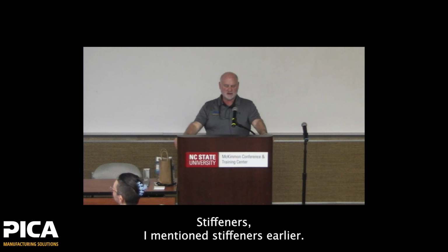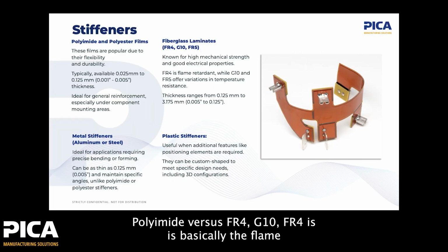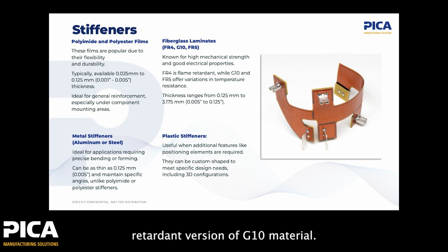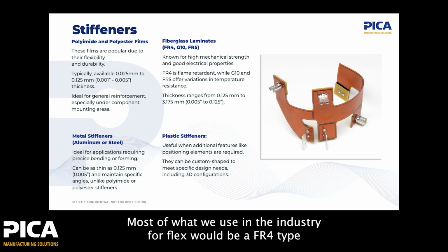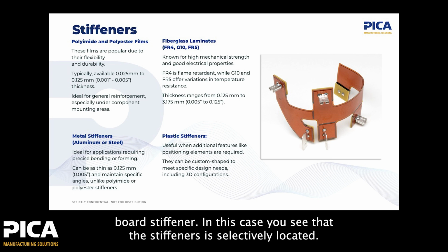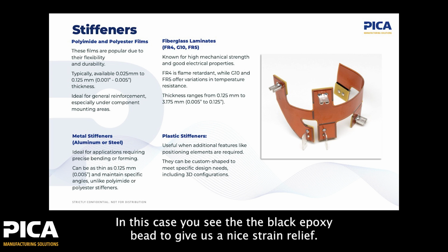Stiffeners. I mentioned stiffeners earlier, Polyimide versus FR4, G10. FR4 is basically the flame retardant version of G10 material. Most of what we use in the industry for flex would be an FR4 type board stiffener. In this case, you see that the stiffener is selectively located. In this case, you see the black epoxy bead to give us a nice strain relief.